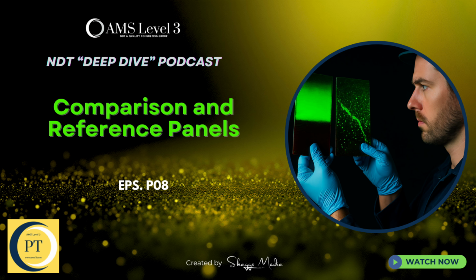And it's a necessary challenge, because the reality of manufacturing is pretty staggering. When engineers first started looking for process-induced cracks in, say, aircraft parts, what they found was shocking. Some titanium-forming cracks were as small as 7 micrometers. That's 0.0003 inches, incredibly small. 7 micrometers is already hard to wrap your head around, but you said it gets even smaller. Oh, yeah. Some stainless steel welding defects, down to 2 micrometers, too.